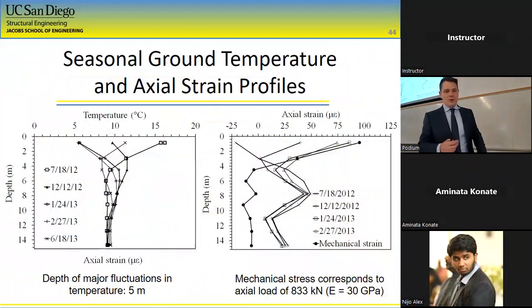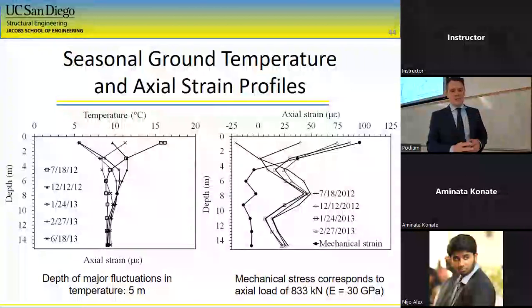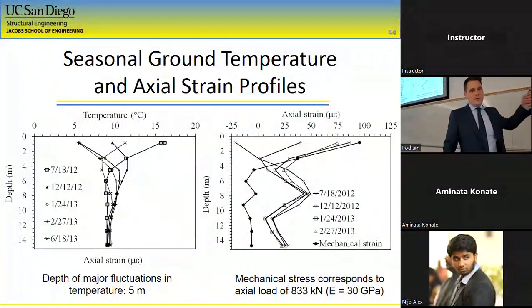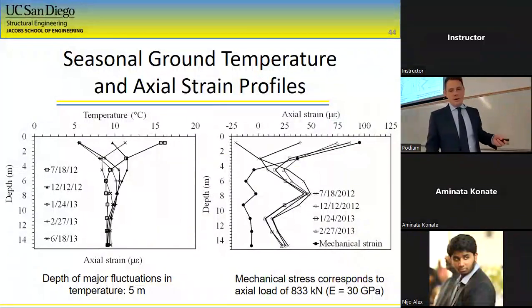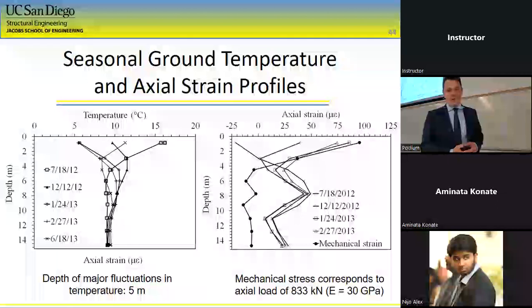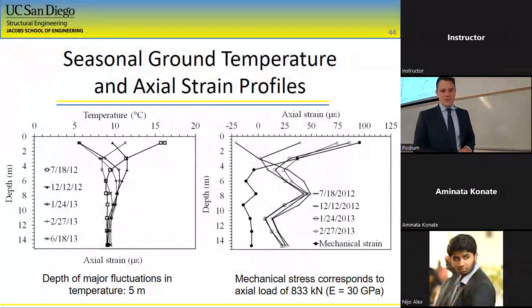And then while they were building the building, we tracked the change in temperature. You can see that if you're below about 5 to 6 meters, the temperature is relatively constant, equal to the mean annual air temperature. We looked at the temperatures during curing, and we separated those off, and then the mechanical strains due to the building load. So we were able to carry the entire building load in the first 4 meters. It didn't need to be 15 meters deep.